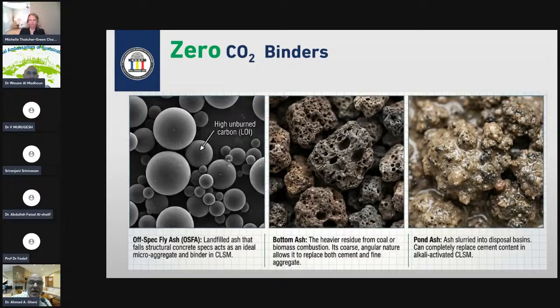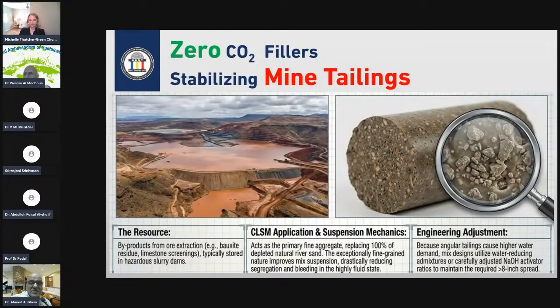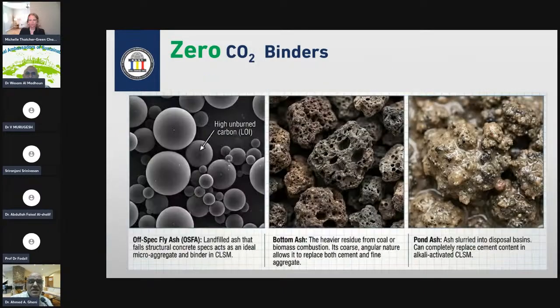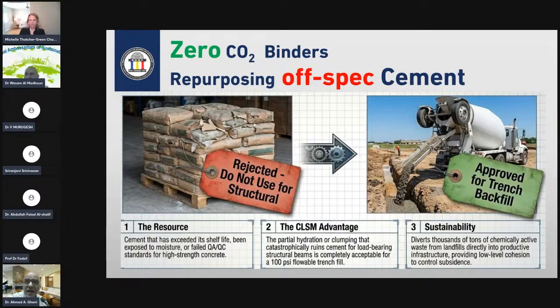So it's not transformed to fly ash. And pond ash. Pond ash is, if we go to the next slide over here, when they store or just deposit the fly ash, that is the leftover of it. And when it comes to the off-spec fly ash, there is a type of fly ash that cannot pass the test and the standard due to lack of consistency or required chemical composition, physical composition, unburned material, all of that. Those are the stuff that, till now, there is no application for them to be used with.